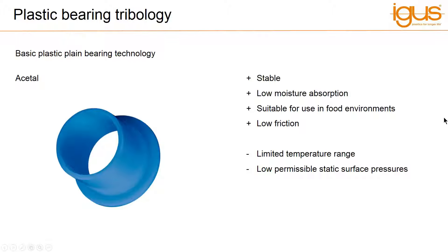Acetal, as a basic material, is a good general-use product. It has good friction characteristics and is easily machinable when manufacturing special parts. Compared to nylon, it has better resistance to moisture absorption and demonstrates low wear in medium-to-low load and speed applications. From a tribology point of view, the benefits are lower wear and friction and therefore longer component life. It also has the added benefit of being food safe, especially when coloured blue, making it the regular choice in the food and packaging industry.